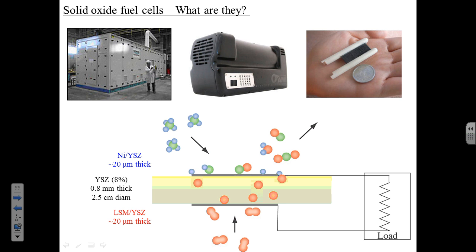And so there's a green top to them. The green top and the black bottom are the anode and the cathodes. So a solid oxide fuel cell, there's an anode, typically nickel. The green color that you see on these things is nickel oxide. We reduce once we get up to temperature. And we have a cathode, which is a lanthanum, strontium, manganate material. So this is a perovskite. And then a solid oxide electrolyte. These are electrolyte-supported cells. So that solid oxide is about eight-tenths of a millimeter thick.